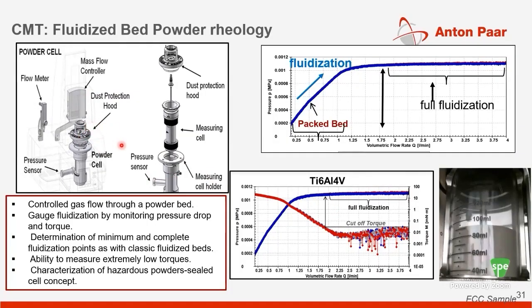And this slide hopefully shows you the incorporation of a powder rheology accessory on the rheometer. It has a pressure sensor and a mass flow controller, and there's a bottom glass frit through which you can send controlled amounts of air. And you can do classical fluidized bed type experiments where you can get pressure drop as a function of volumetric flow rate, and characterize your packed bed and fully fluidized regions. And I show you some data for an additive manufacturing powder here.